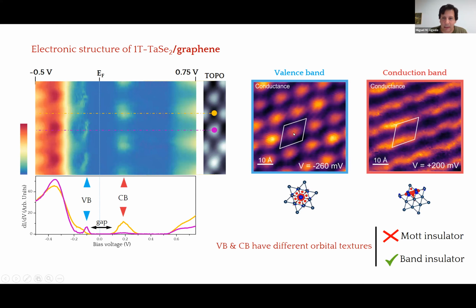So the valence band is localized at the center of the star of David, as expected for the Mott insulator, but the intensity of the conduction band is not located at the star of David, but in the outer part of the star of David. This is not consistent with a Mott insulator, and it's only consistent with a simple band insulator.